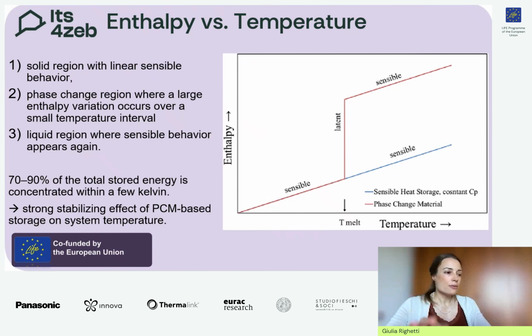If we look at this graph, the enthalpy temperature diagram, we can see this behavior. As the PCM receives energy, we have three regions. The first one is a solid region with a linear sensible behavior, so we have a temperature increment. Then we have the phase change region, where a very large enthalpy variation occurs over a very small temperature interval. And finally, the third region is a liquid region where sensible behavior appears again, so temperature rises with an enthalpy increment.